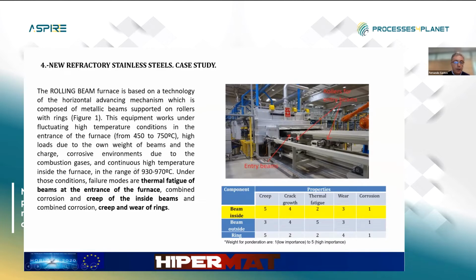Under these conditions, failure modes are thermal fatigue of beams at the entrance of the furnace, combined with corrosion and creep inside the furnace, and combined corrosion, creep, and wear of rings. So this is something we have evaluated, which are the main conditions. We are going to go over the beam inside the furnaces, which currently represents quite a regular failure mode that generates shutdowns in the plant. The goal has been to improve creep mainly and crack growth rate. These are the two main issues that are affecting these beams.